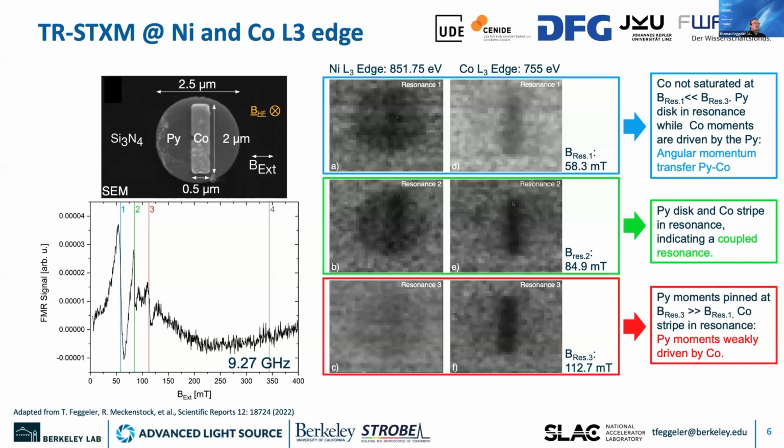And finally, the main resonance of the cobalt, which we have seen before. Here we have a similar situation, where the cobalt now weakly drives the permalloy magnetic moment into a weak precession. Weak precession means that at this relatively high field, most of the permalloy moments are already pretty much aligned to the external field, therefore just this weak response.